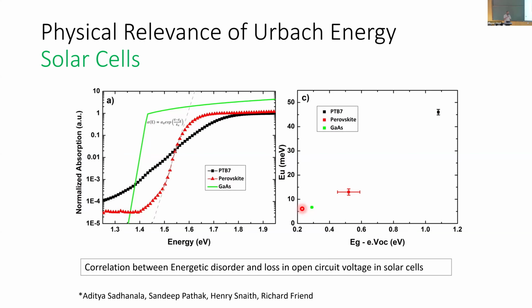And before I make solar cells, I correlate the voltage that I get in my solar cells. The real voltage you get in a solar cell ideally should be equal to your band gap, but there's always a loss associated with that. If you correlate the Urbach energy with respect to the voltage loss relative to the band gap for any semiconductor, you see that lower the Urbach energy, lower this loss. So that's a very easy correlation to establish.